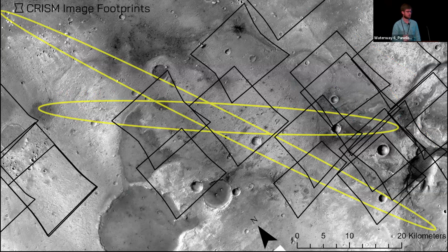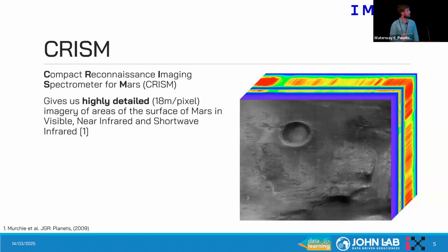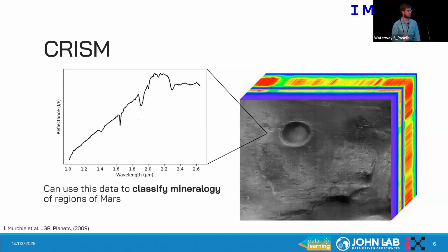There's quite a lot of CRISM data over the area, which gives us some idea of the mineralogy of the surface. CRISM data gives us pretty detailed, at 18 meters a pixel, spectroscopy data of the surface in visible through to shortwave infrared. We can extract spectra from each pixel and identify key absorption features to figure out what the mineralogy of the surface is.